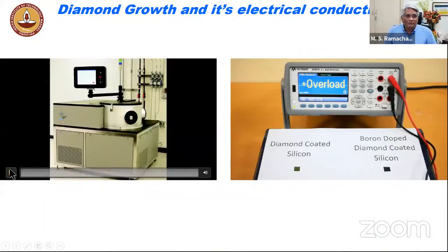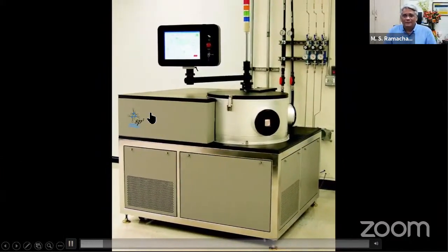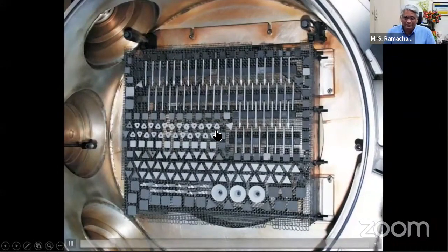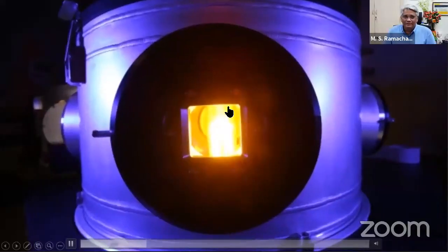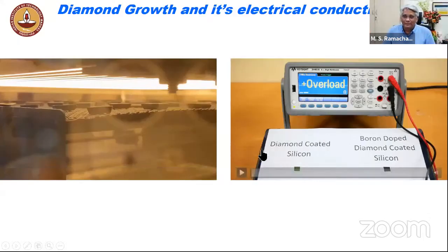Now, this small video clip, this is a unit that is used for creating diamond. This is a hot filament CVD. The name itself suggests that you have hot filaments, tungsten filaments heated to almost up to 2,300 degrees centigrade, and methane is a gas there, the precursor gas. And then you see the formation of diamond on the substrates that are kept at a distance below these hot wires, made of tungsten. What you see on the right-hand side is a small, interesting clipping of you have 2 substrates there, one diamond coated on silicon, and the same diamond with the boron incorporated into the lattice. And you see what happens.